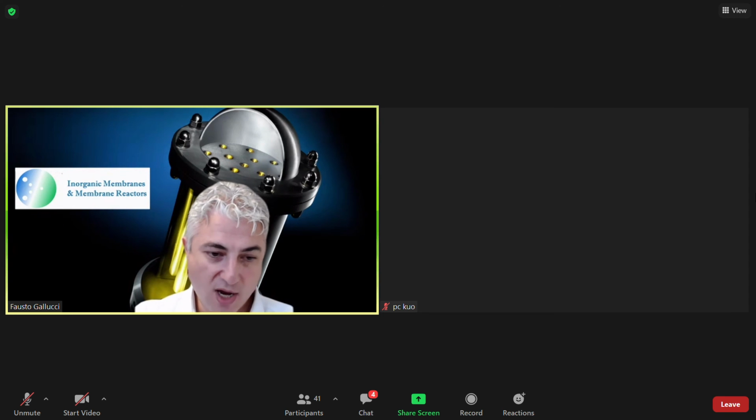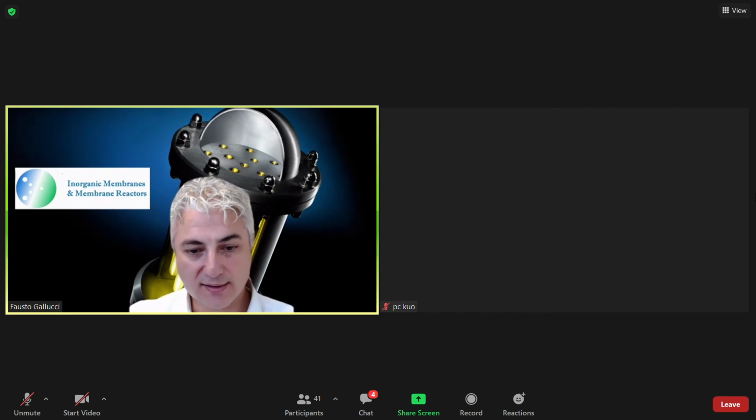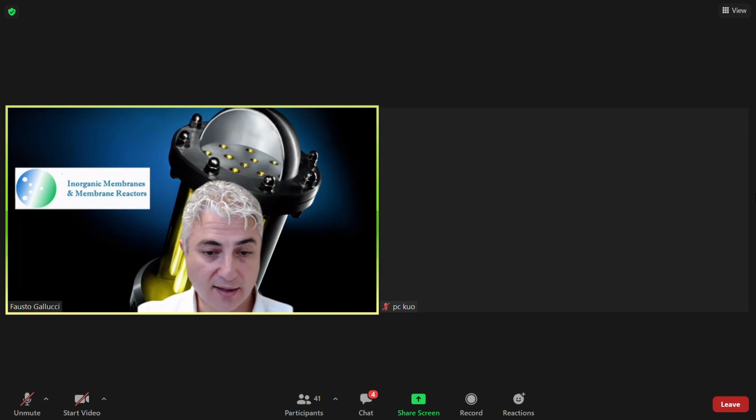We know that if we are able to decrease the temperature a little bit, then the membrane stability is higher. If we are able to work below 500 degrees, then we have many thousand hours without any degradation. We believe that we solved the problem of fluidization with this protective layer.